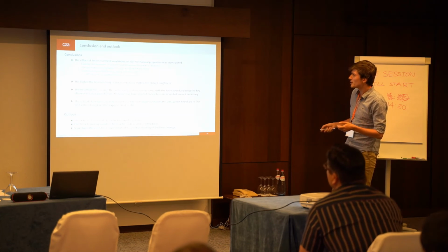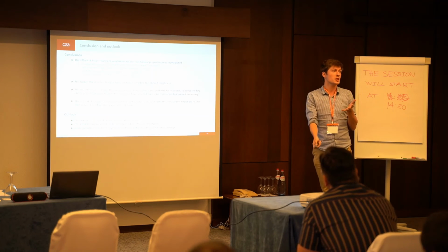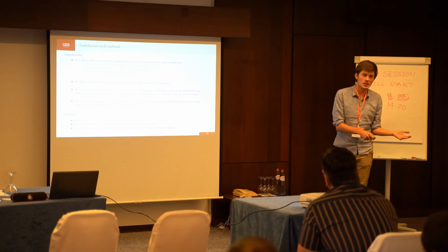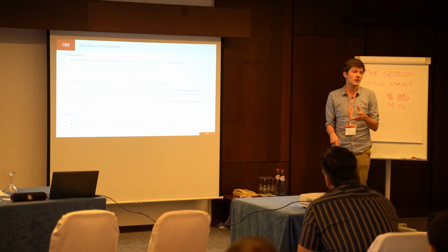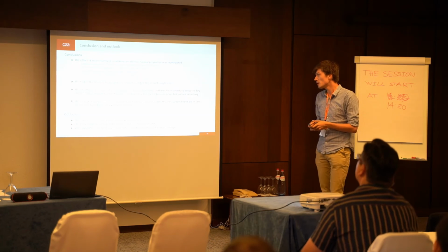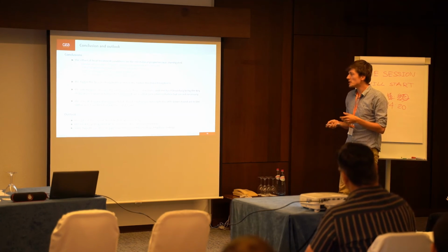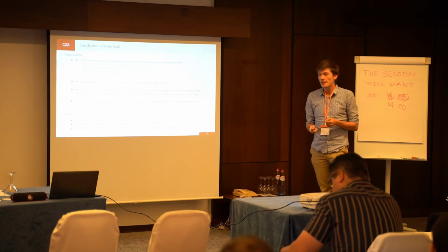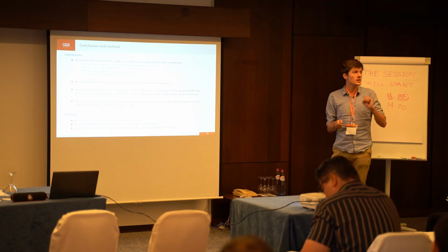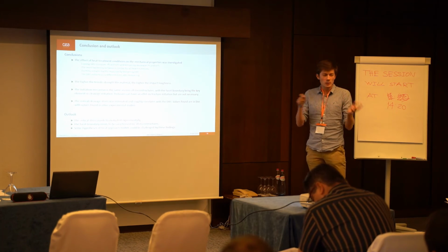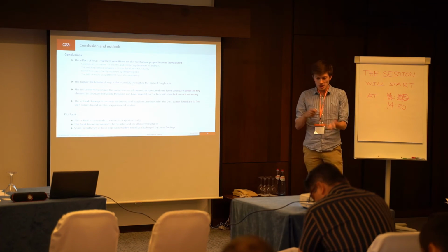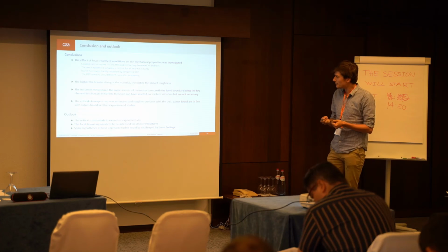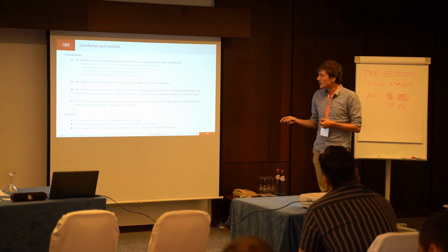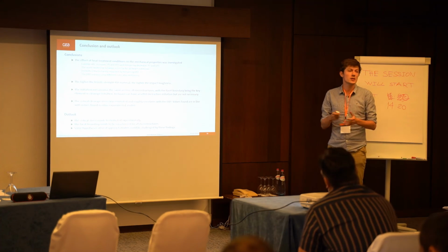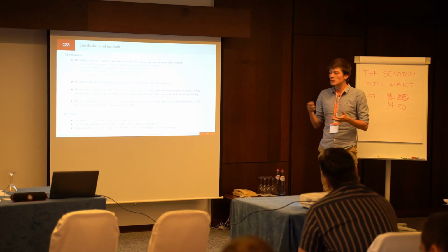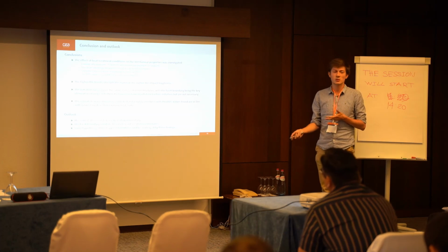So to summarize, in this study, we have explored the effect of treatment conditions on mechanical properties, both tensile properties and impact toughness properties. The higher the tensile strength, the higher the impact toughness of the material. For all materials considered, the initiation mechanism is the same across all microstructures, with the facet boundary being the key element in the initiation of cleavage. Some secondary phase can have an impact on the initiation, but it remains to be investigated. Also, we estimated the critical stress for cleavage based on the impact test instrumented curve, and it roughly correlates with the different transitions that you observed.